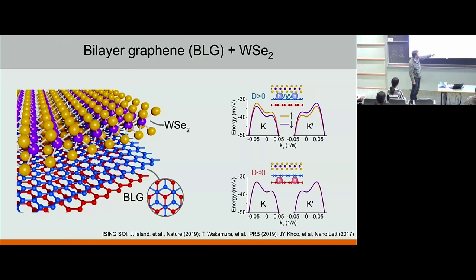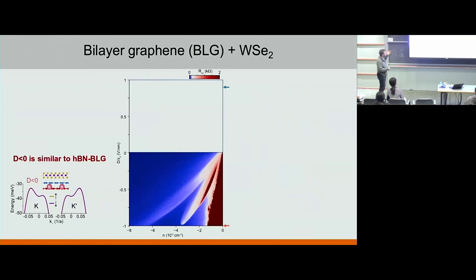And if you do the opposite displacement field, you essentially get just a normal expected band structure of graphene. This already suggests, and I will come back to it, that other spin-orbit couplings like Rashba are at least not in this picture, and I'll touch upon later how much they should be. We know that Rashba is not super big,